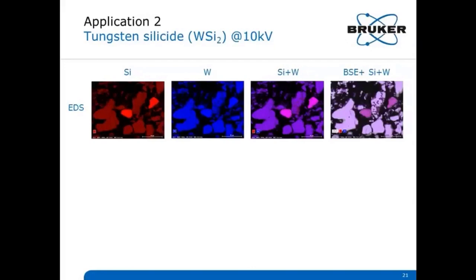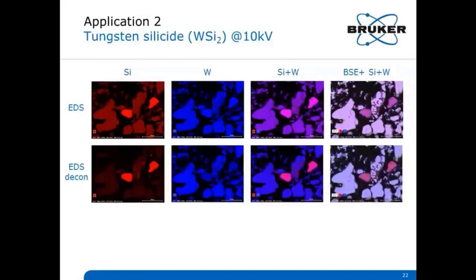We see silicon in red and tungsten in blue, and we see that there's some difference in respect of the silicon content. Two particles are obviously somewhat different in composition from the rest. They clearly seem to be higher in silicon content. Here we see the result of EDS deconvolution. Deconvolution suggests that many particles have a low silicon content, except for the two particles, but all particles have tungsten, also the two silicon-rich particles.